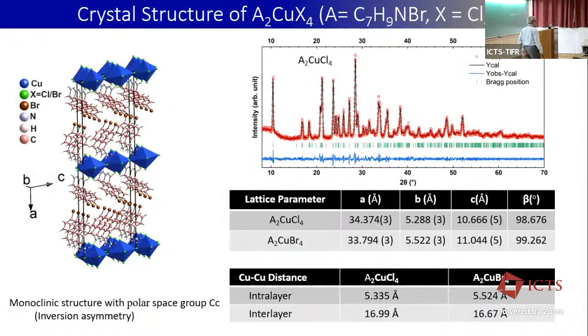So motivated by this work, we tried to grow single crystals of two new materials belonging to this family, where in one case the ligand is chlorine, and in another case the ligand is bromine. I will not get into the structural details, but one point I want to point out is the following. As you go from chlorine to bromine, because bromine is a larger ion, the copper-copper distance increases. So you see here you are going from 5.33 to 5.52.